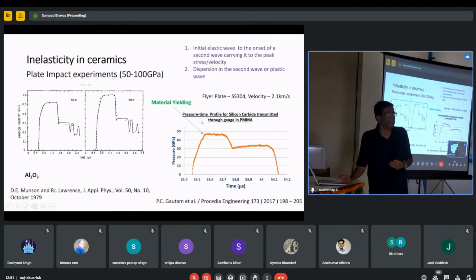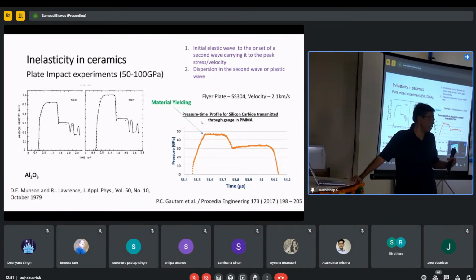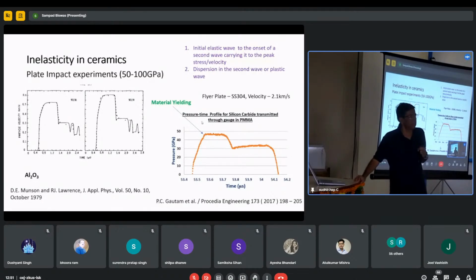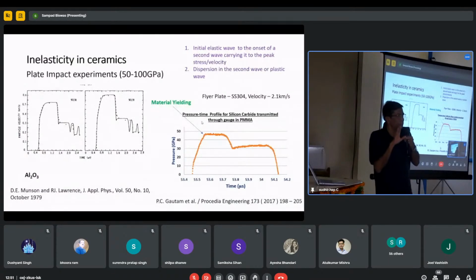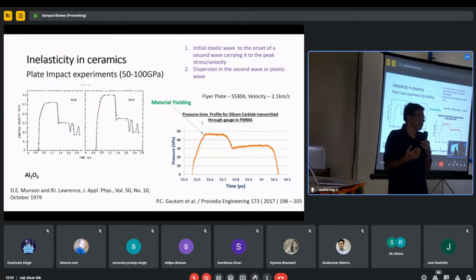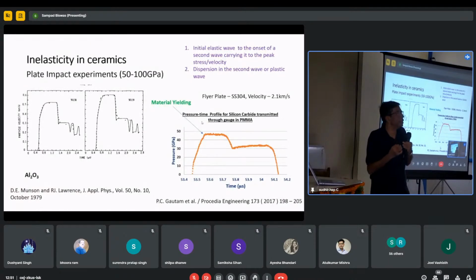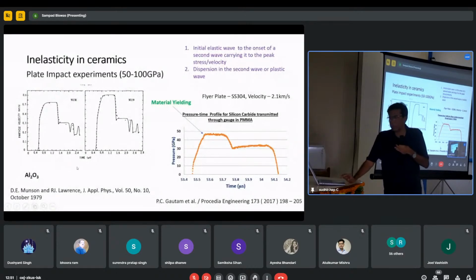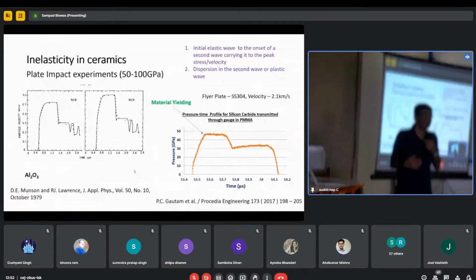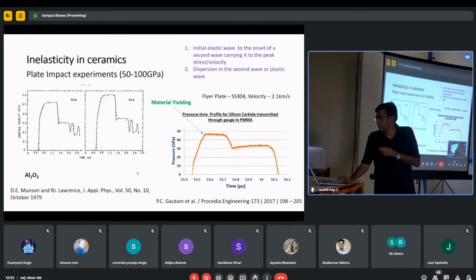Now, inelasticity of ceramics was first studied by planar shock experiments. Planar shock experiments means you apply a planar wave to the ceramics and then follow the response. These responses are followed by means of a manganin gauge or piezoresistive gauges. And you get the particle velocity against time, and you get a shock Hugoniot also. So Hugoniot characteristics are very important in the case of armor ceramics.